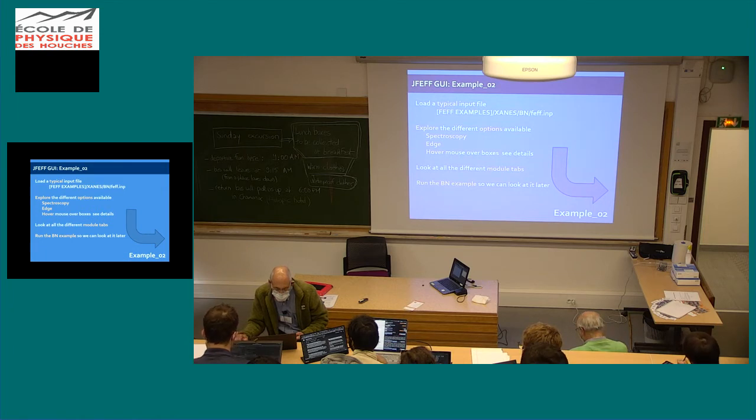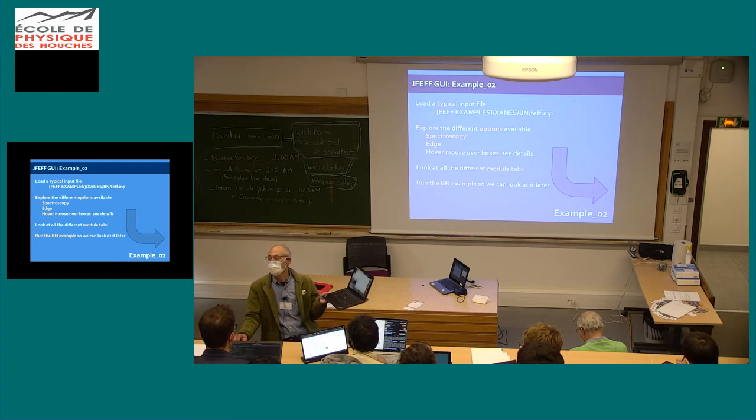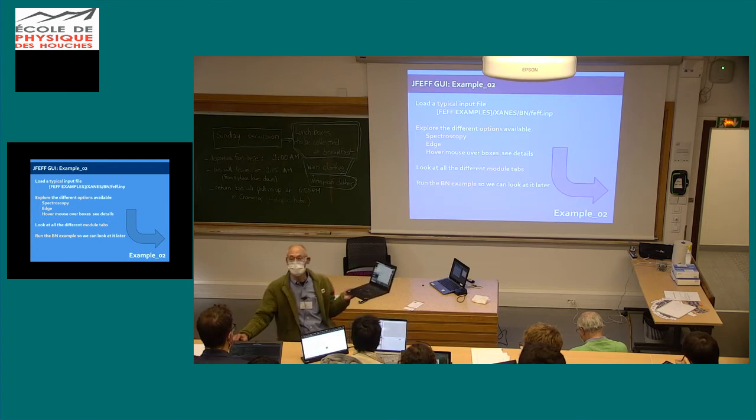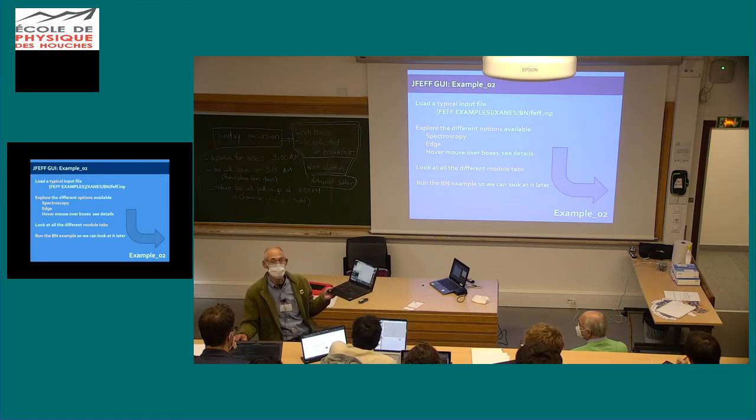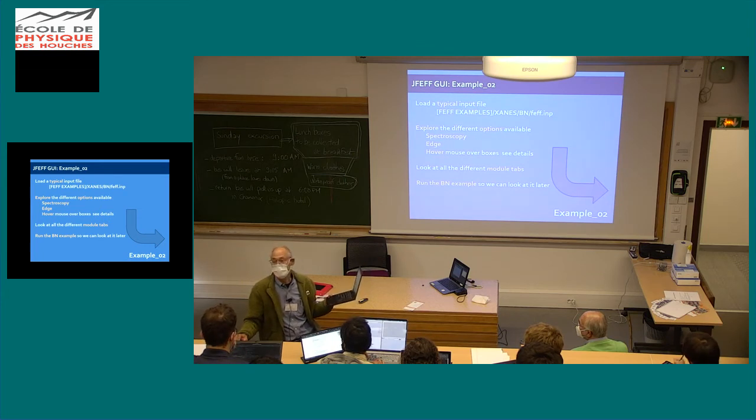And if you look at the core hole, it gives you some options too. The final state rule is the default. That's a real, just self-consistent DFT screening. Or there's an RPA, or there's nothing if you don't want a core hole in the calculation. It's interesting.